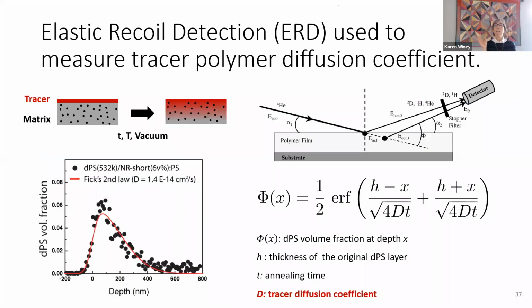So again, elastic recoil detection can tell the difference between deuterated polymer and regular polymer. So you put a little deuterated polymer on top of a nanocomposite, you can watch that deuterated polymer diffuse in and measure its concentration profile. This is actually a lot easier to do in the nanocomposites than it was in the AAO templates. Much better signal to noise.